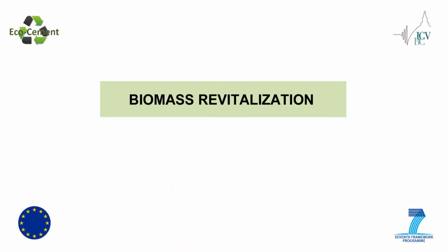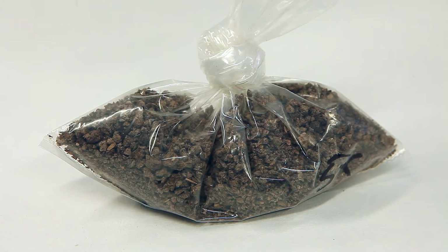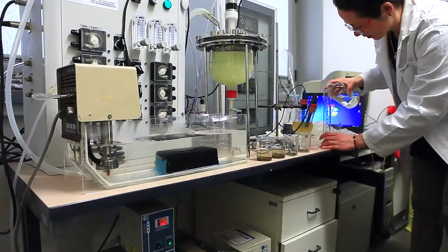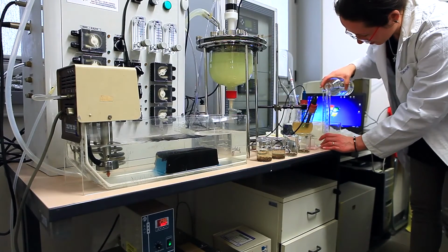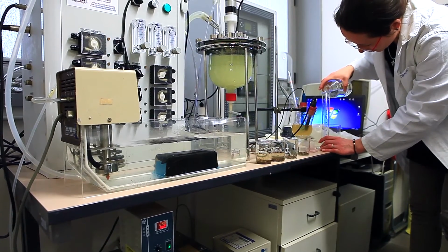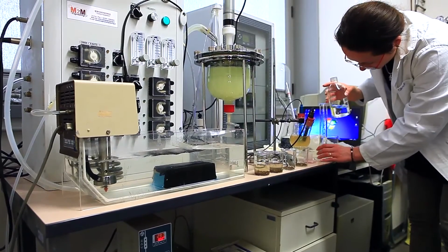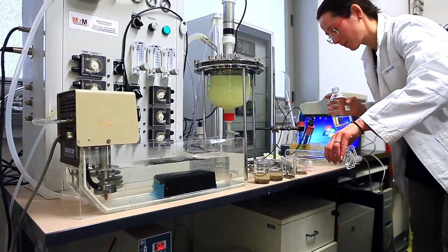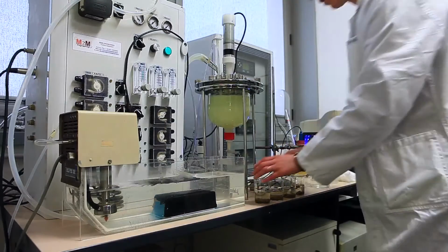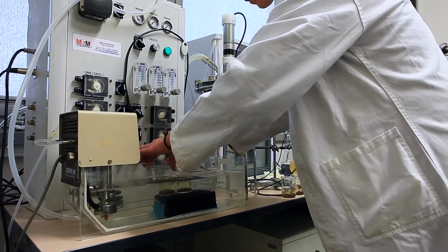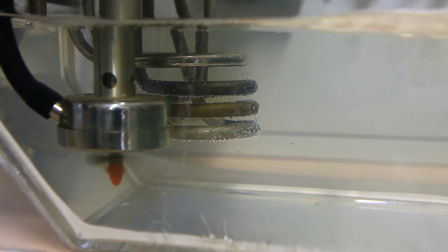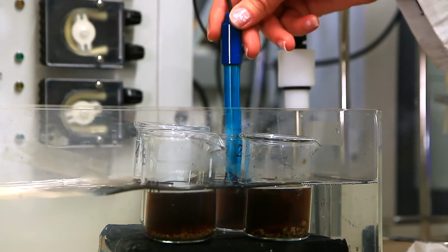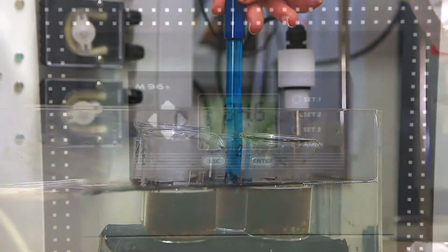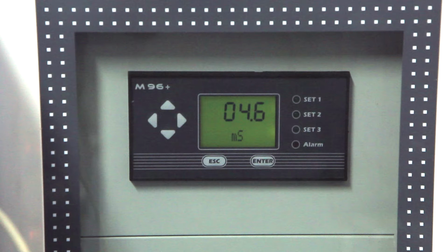The first operation is the revitalization of the bacterial biomass needed for the urea hydrolysis. The dry matter composed by Sporosarcina pasteurii is ripened in dry poultry manure and soaked with a solution of whey, a waste from the dairy industry, and agricultural urea. The containers are placed in a water bath at 30 Celsius for 3-4 hours, and the conductivity measurement is used for controlling the level of bacterial activation.